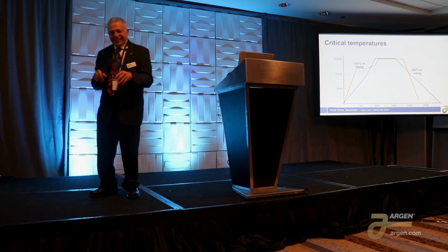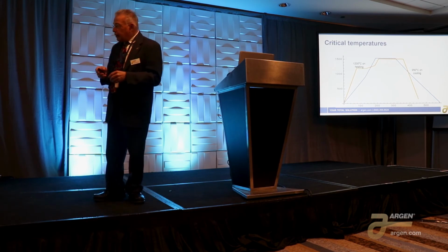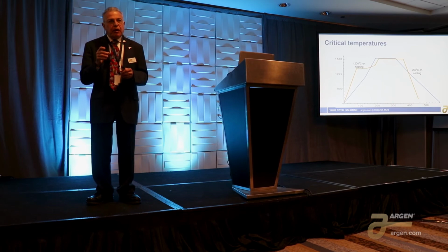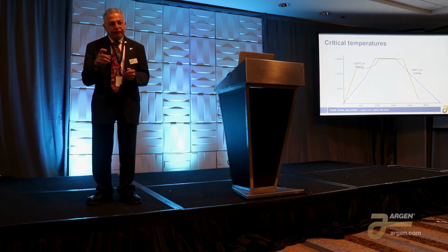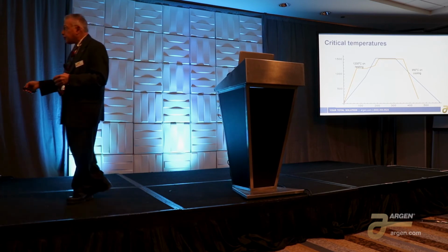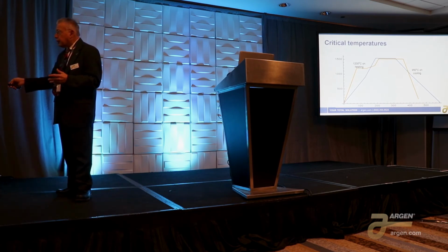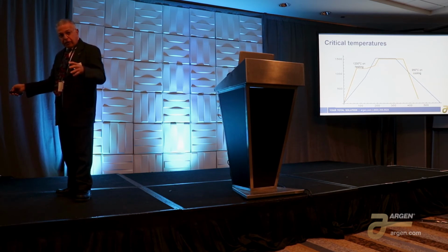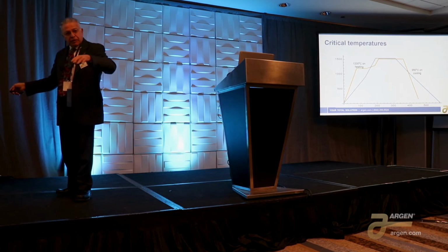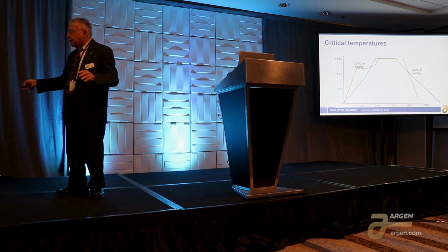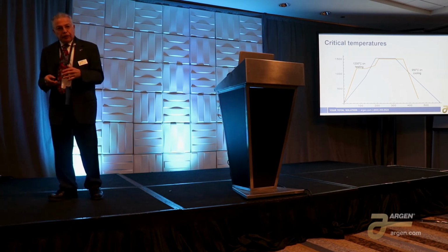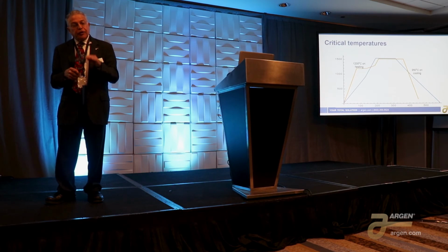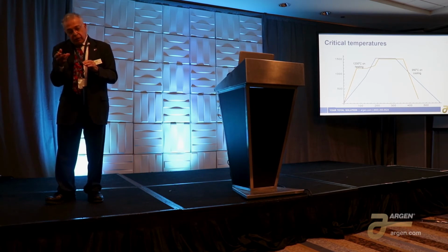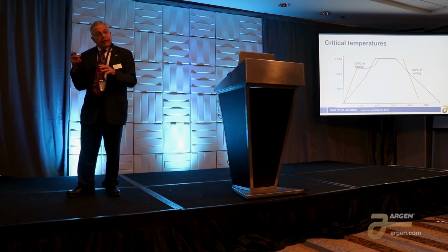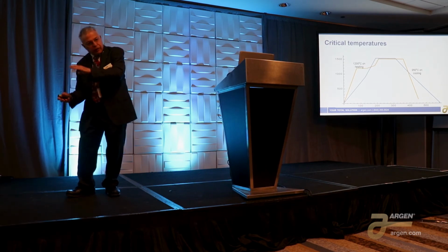Let's reference it. The significance of the 950? The 950 is the temperature at which the zirconia becomes very sensitive to thermal shock. Most of your programs are going to be slow at the 950 from the sintering temperature, let's say 1500 or 1550 down to 950. You're going to naturally put that down at 7 degrees a minute, 10 degrees a minute, something like that. But once people get below this temperature, they try and go a little faster. And 950 is very critical for the zirconia because it transforms at 950. And that transformation could cause a crack. And that gives you what we call a thermal crack. So that's why when you want to glaze it, you don't want to get close to 950. You want to stay below that temperature.